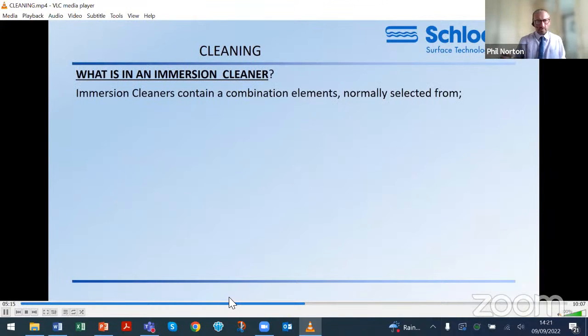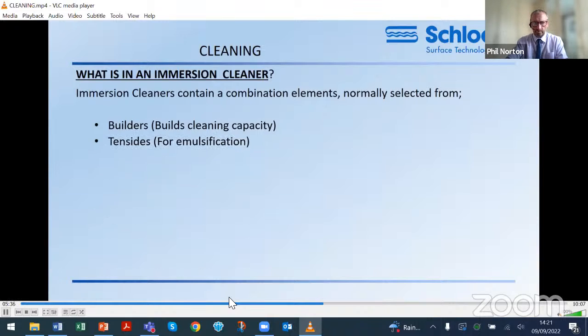So, what's in these cleaners that make them so effective? Immersion cleaners are a combination of chemical elements, typically, but not all, of the following. Builders. These build cleaning capacity, the basic building blocks to support the functionality of the cleaner. Tensides for emulsification. In other words, these ingredients encapsulate oil and grease so that it can be removed from the surface. Alkalinity. Strong alkalis chemically react with oils to make them soluble in water.